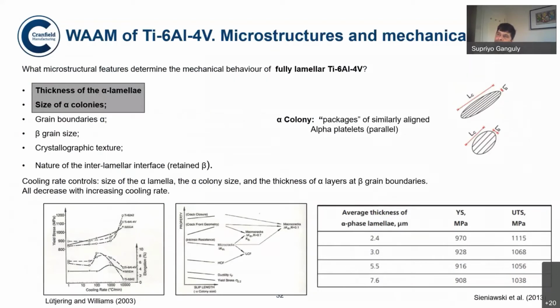So a detailed microstructural study was carried out, which I'm not going to talk about here, but I can guide you to all the different papers at the end, which will show the reason for this variation, where the thickness of the alpha lamellae, which titanium 64 is a two-phase alloy where most of the part is alpha and there is some amount of beta. So it was shown that the thickness of the alpha lamellae and the size of the alpha colonies are basically responsible for the differential strength that was generated in the different building strategies.